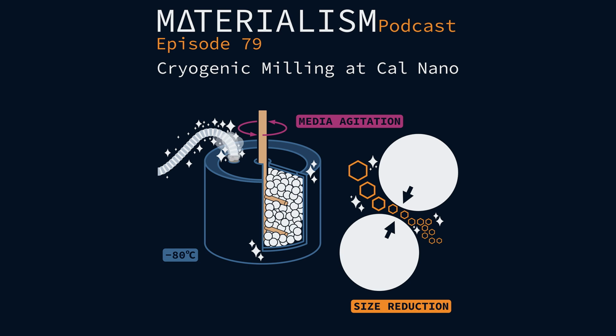And so you can create some really interesting and unique materials this way that just would be incredibly difficult to otherwise. And I'm sure that impacts sintering as well. Like, I think of recovery, recrystallization, grain growth, right? We cover that in intro to MSE. We know that a more damaged lattice has a higher strain, right? There's a strain energy that is embedded into that lattice the more defected it is, and that increases your driving force. That's a driving force for sintering, right? You should lower your energy for sintering. I would expect that you would see an impact on sintering as you increase the cold working in these things.